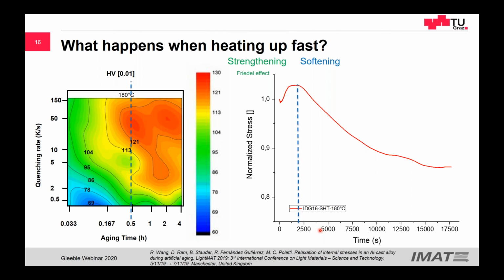We are studying this microstructure, so we have done EBSD of all these things here. But the most important thing to remember is that this is not only a relaxation of a pure aluminium, it's a relaxation and aging. So we also spent a lot of time studying the precipitation, the precipitates formed here with TEM. So we have done TEM and EBSD in parallel. And we also have seen dislocations in the material after quenching, which was very, very surprising.